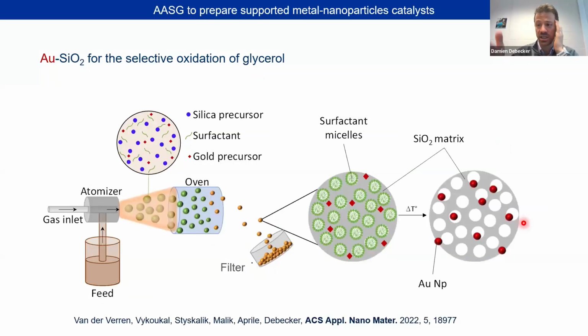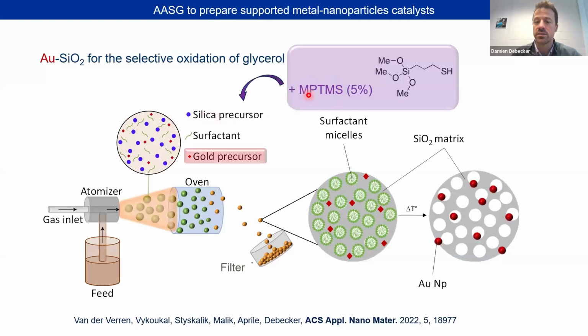So we had the idea, actually, Margot, the PhD student, had a great idea to replace a very tiny proportion of the silica precursor with another one that is called mercaptopropyltrimethoxysilane, with a mercapto group here. And mercapto groups or thiols are known to interact very strongly with gold. And so we hoped that it would stabilize the gold and have something more dispersed at this stage that we can then calcine to form the nanoparticles with the right size. And this is exactly what happened in the end.